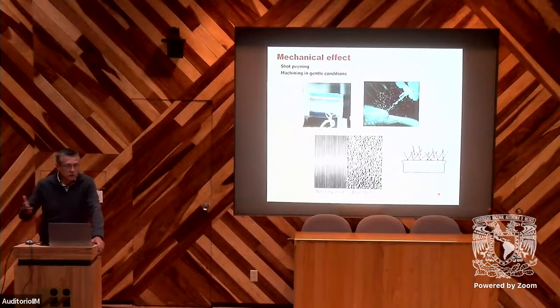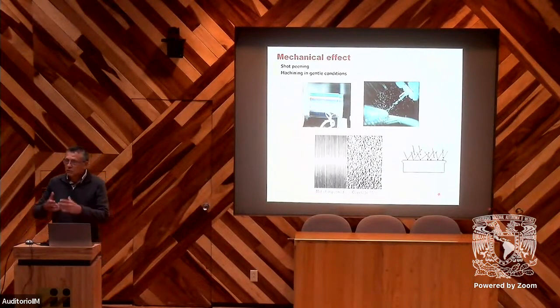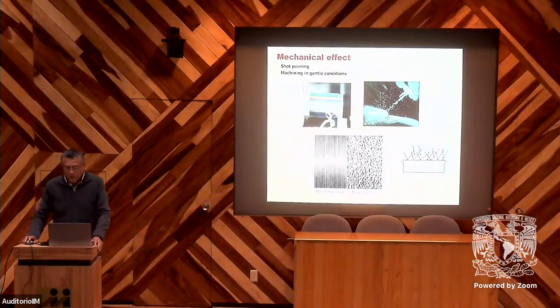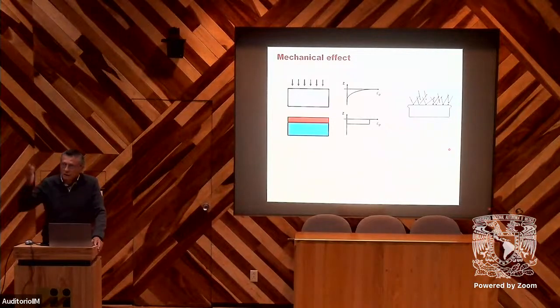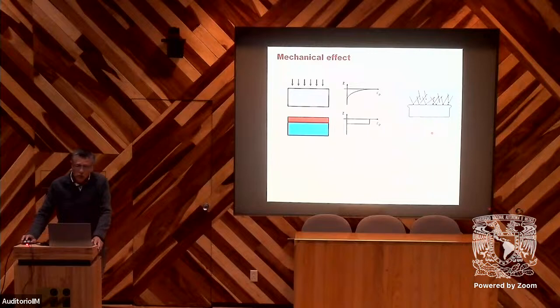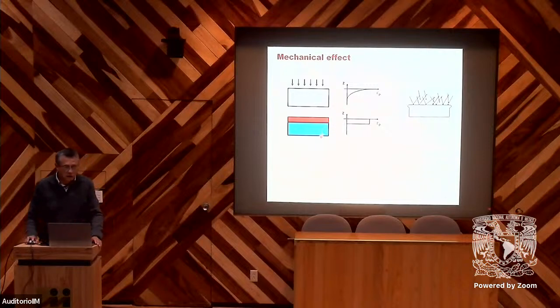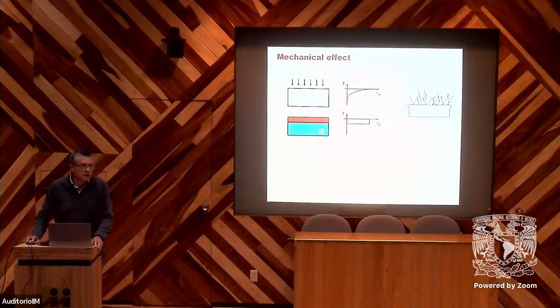Okay. So now let's see all these parameters, and first the mechanical effect. If we consider the case of shot peening or machining in gentle conditions, that means with very high efficiency of cooling, in some cases we can get a preponderance of the mechanical effect. That means we cannot take into account the thermal effect. So in this case, we will get a gradient of plastic deformation. Of course, we can make complicated analysis, but let's take a very simple consideration here. We can consider that we have only two parts, the surface layer and the bulk of the material. That means we have a difference between the deformation in the surface layer and in the bulk of the material. So if we make, for example, shot peening, we will have deformation of the red part.